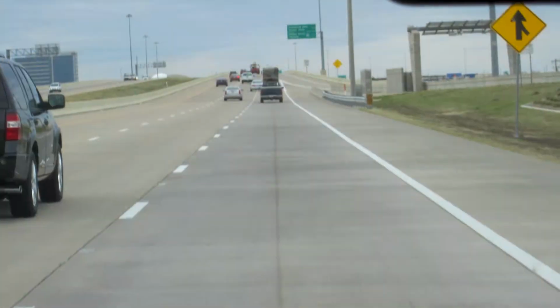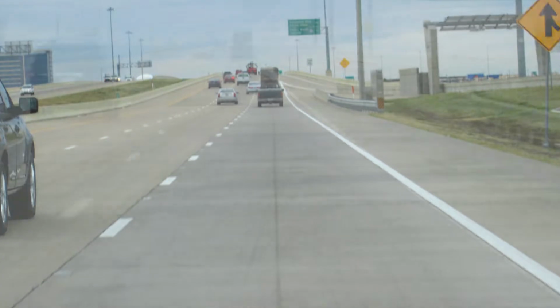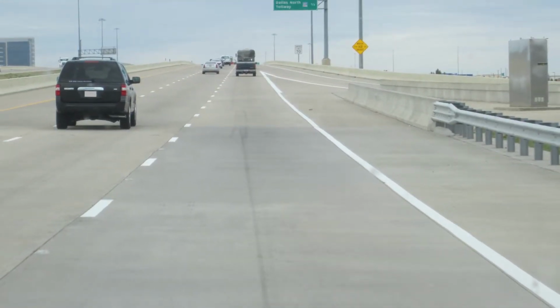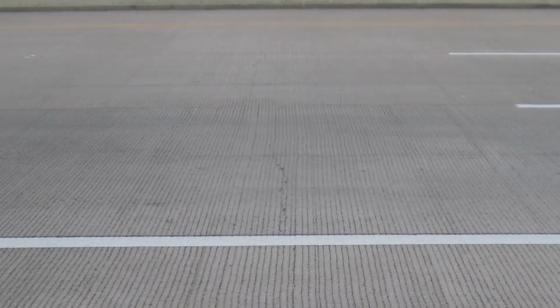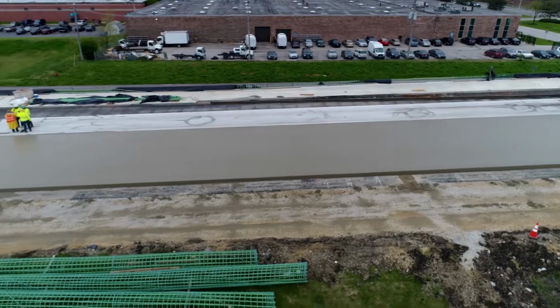One example of an internally cured concrete pavement is a test section on State Highway 121 near Dallas. This continuously reinforced concrete pavement was constructed in 2006. Initially, the cracks in the pavement had a larger spacing than that of conventionally cured pavements. After several years, the crack spacing was similar to that of conventional sections, but the cracks remained tighter. But they learned from that project that it developed different crack patterns. Tighter cracks were developed on those pavements. Also, to reduce curling and warping strains on the pavements, it's another reason why we're looking into this as well.